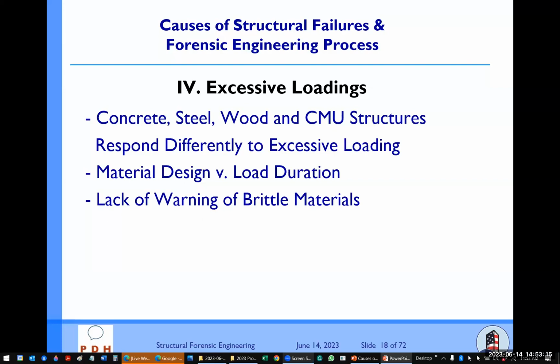That's in NDS. When you only have dead load, the load duration factor goes to 0.9. So instead of 125% of allowable stress, you get a reduction, and it goes to 90% of the allowable stress. So let's say it was 1,000 PSI; instead of 1,250 PSI, it drops to 900 PSI. And I've seen with my own eyes a building collapse like that. Specifically, a solar panel installation, where instead of a screw, they were adding dead weight for the uplift. So that's one thing you want to keep in mind.